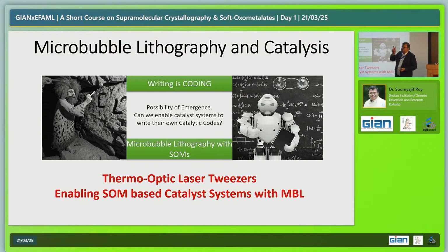That's very good. There are two types of things which are important to keep in mind in catalysis. One is the pre-catalyst and the other one is the active catalyst. What you normally add in your reaction, or electrochemical reaction, or any reaction, is the pre-catalyst. That is not the active catalyst.